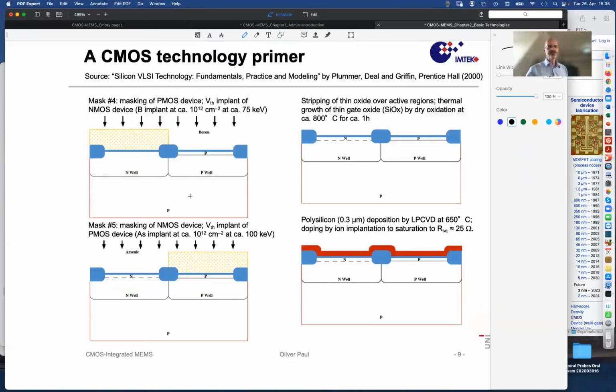And then after that, we do the same for the P channel devices on the left, where we protect again the right-hand side with photoresist, and do some arsenic implant, again 10 to the 12 at 100 kilovolt. Remember that this was 300 kilovolt before, deep, to go really deep with the well, and now we are doing something quite shallow.